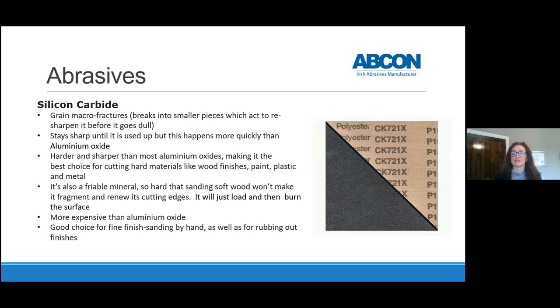So this basically resharpens it before the material goes dull. So it stays sharp right up until you've used up the piece of sandpaper, but you'll use it up faster than you would aluminium oxide. It's harder and sharper than most aloxes, which makes it the best choice for cutting hard materials like wood finishes, paint,